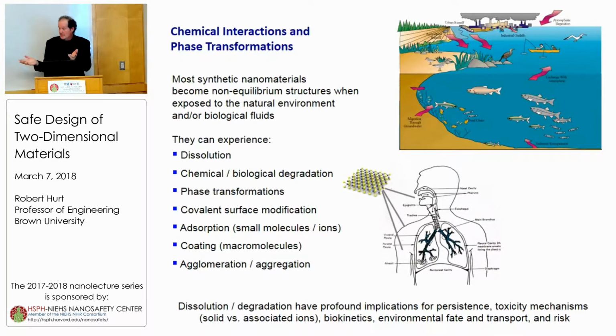One doesn't make unstable materials because they can't be used for anything, but they're stable under the conditions they're formed, and they may be stable on the bench at room temperature. But if you take them out of that environment and you put them in ultra-dilute conditions, in media with reducing agents and with oxygen, which is ubiquitous in biology, you get transformations that include dissolution, degradation, sometimes phase transformations. And there's a kind of a large literature that is developed on this. And our particular interest today is in dissolution and degradation phenomena.